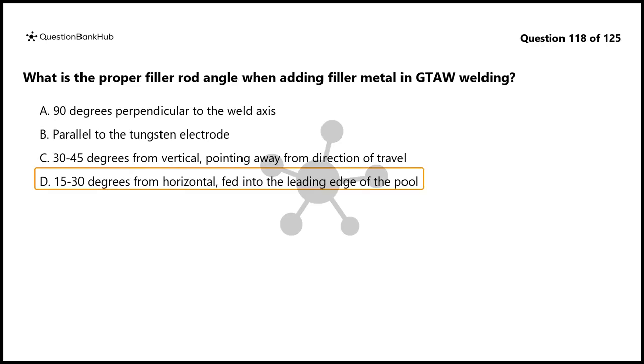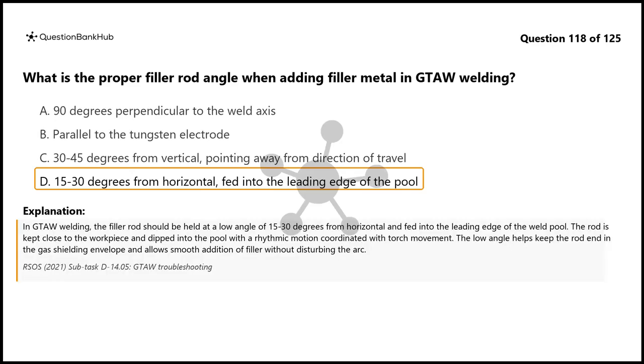The correct answer is D. 15 to 30 degrees from horizontal, fed into the leading edge of the pool. In GTAW welding, the filler rod should be held at a low angle of 15 to 30 degrees from horizontal and fed into the leading edge of the weld pool.